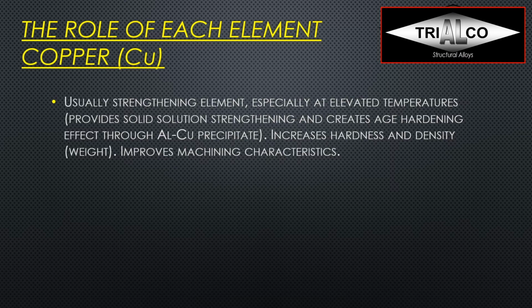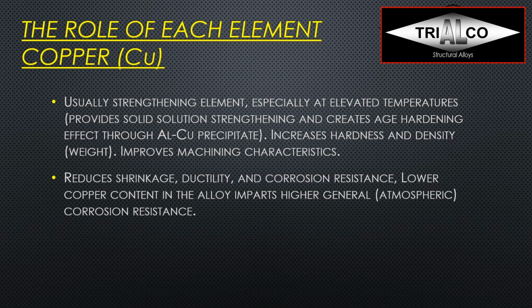Otherwise, I only need it if I want to go to very high strength in the 200 series. It provides solid solution strengthening and creates an age hardening effect through the aluminum copper precipitate. It increases hardness and density. It improves machining characteristics as well. It actually reduces shrinkage, but also ductility and corrosion resistance.